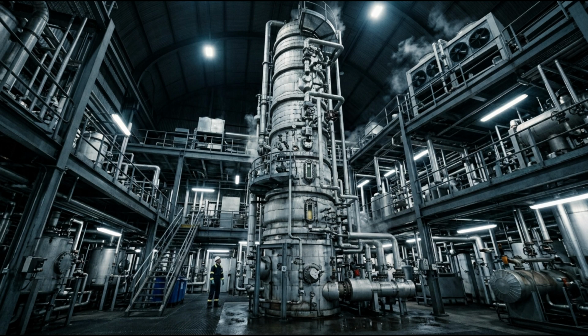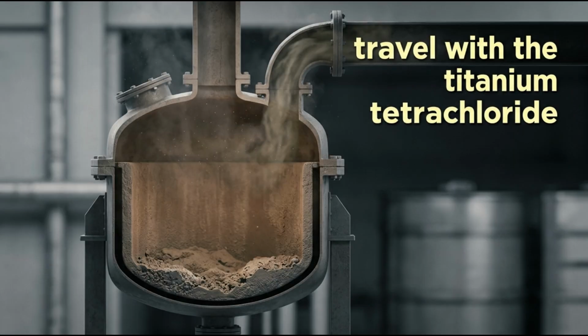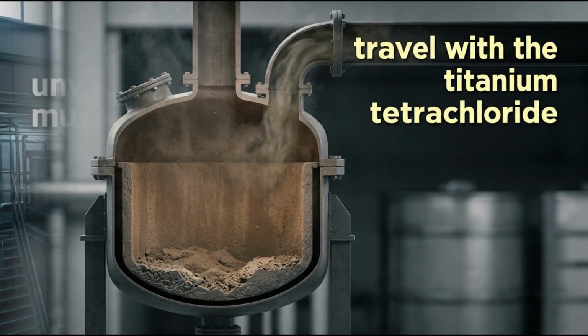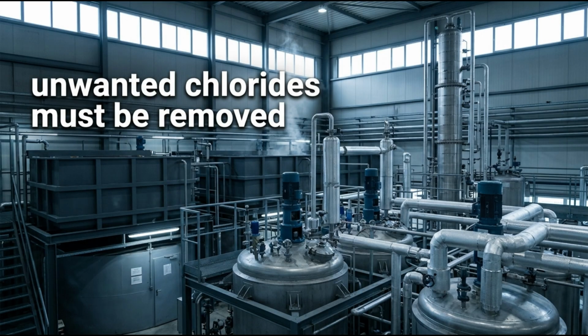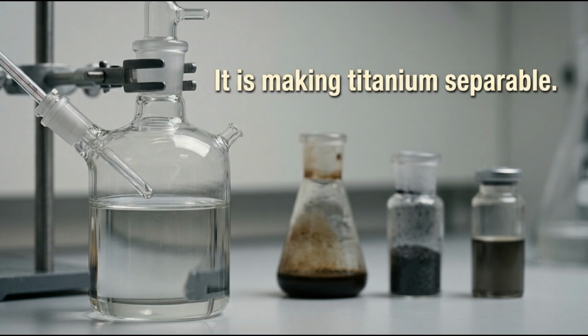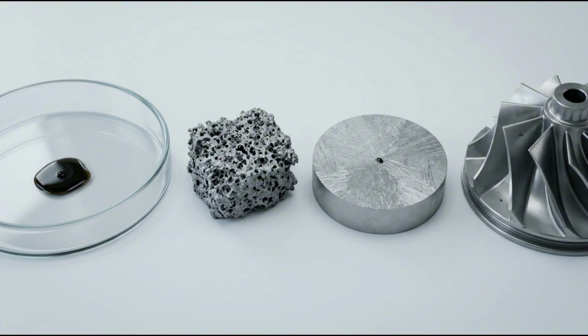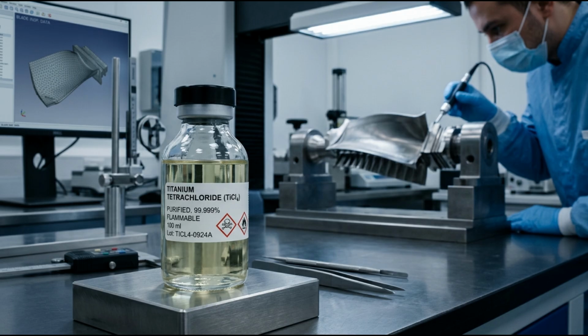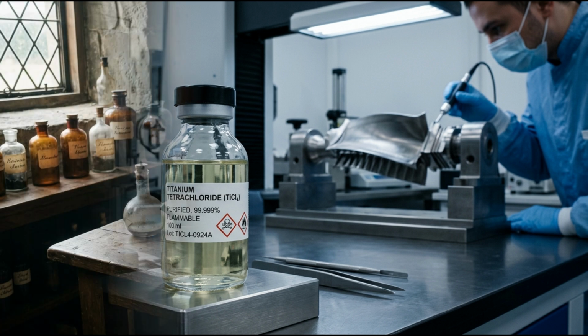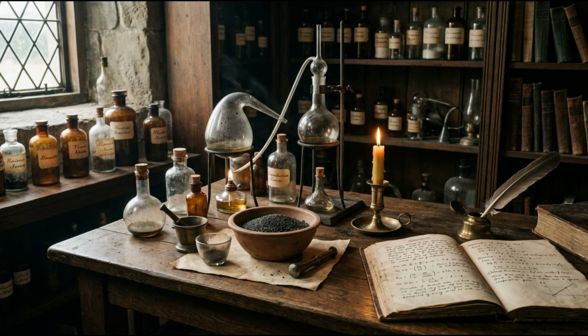Some impurities remain behind as solids in the chlorination reactor. Others form chlorides of their own and travel with the titanium tetrachloride. Those unwanted chlorides must be removed through settling, chemical treatment, condensation, and fractional distillation. The plant is not yet making titanium metal. It is making titanium tetrachloride. That distinction matters because a contaminant allowed through this stage may survive into the sponge, then into the ingot, and eventually into a component placed under enormous stress. The reliability of a finished jet engine part may depend on the cleanliness of a liquid produced much earlier in the process.